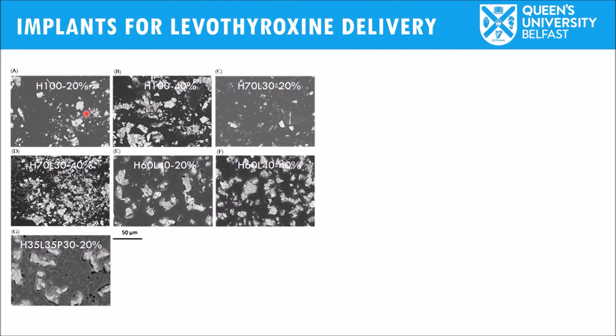It was clear to us, apart from the pictures, that implants containing levothyroxine presented some sort of problems, because the drug crystals had a different shape and the polymer thing was completely different from the other type of implant. That put us in the direction of thinking that there was a degradation, and actually there was a significant degradation of the drug. Whenever we analyzed all the implants using HPLC, we established that we should have recoveries of the drug higher than 85% of the initial drug content. Here that was not the case, so we decided not to use this type of implant and not pursue the use of polyethylene glycol in the formulation.